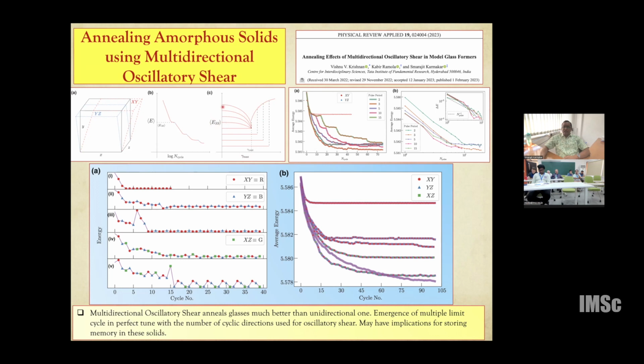And then there is an interesting energy scale. If you start your oscillatory shear below that energy scale, then it turns out that you no longer can anneal the sample using this oscillatory shear protocol. This energy scale turns out to have a very close correspondence with what an MCT energy scale is going to be. And why it is so, we do not have an answer, nor do the others who have worked on this.